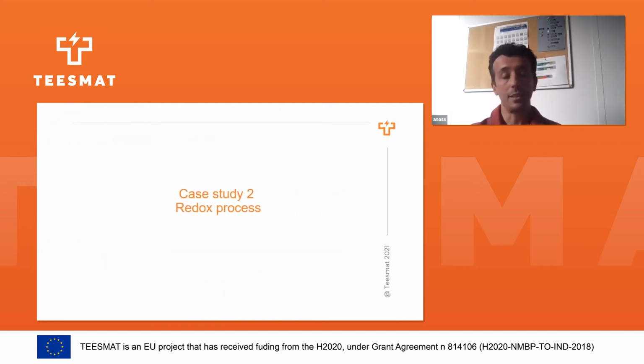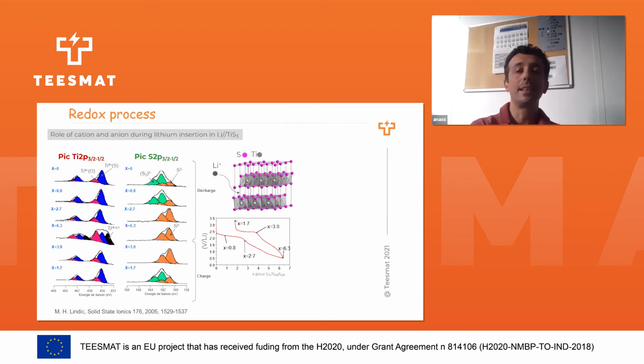The second case study is the redox process. I showed you how XPS can give information about SEI growth or the activity of the surface. Now I will move to the redox process. I will choose the case of lithium titanium sulfide based batteries. Our electrochemical system is lithium with EC-DMC LiPF6 electrolyte, and the positive electrode is titanium sulfide.